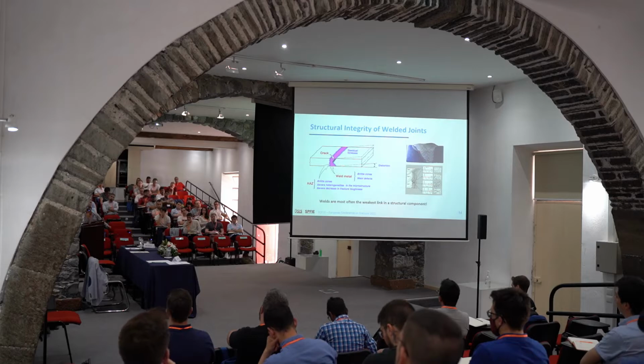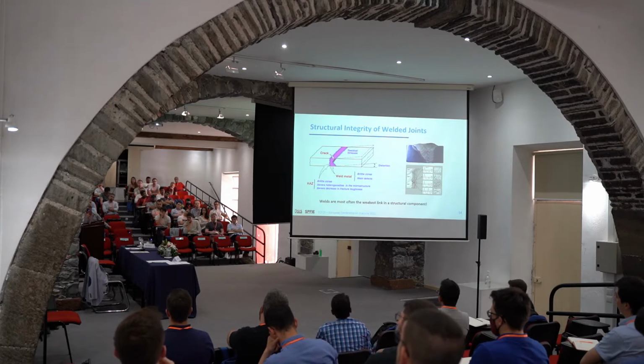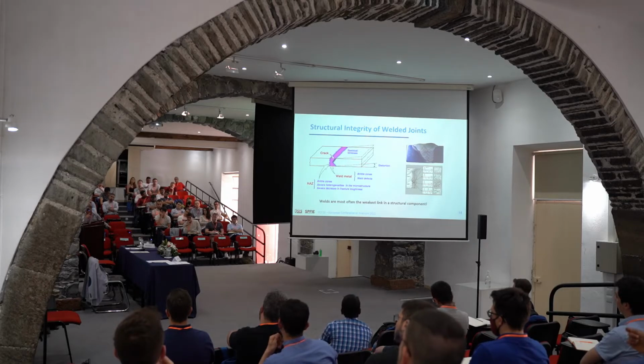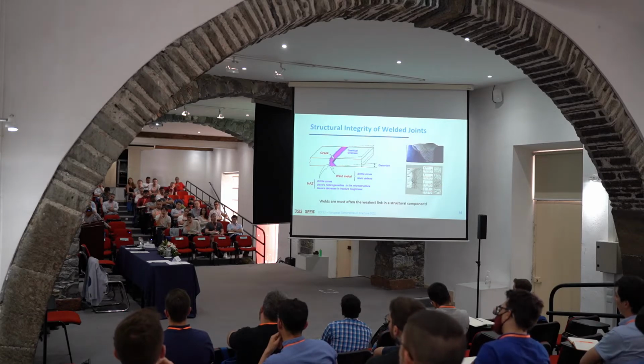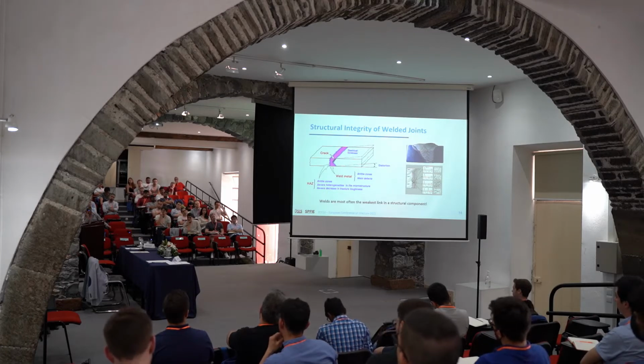If you have, for example, what's the standard way of assembling the airplane fuselage, you have a rivet, the plates are sort of superimposed. So if a crack develops in one panel, it won't propagate to the other panel. That's one of the reasons why the fuselage is not welded, especially for aluminum. Of course, I'm not discussing composites like the new trend. But in most structural components, the way we put things together is by welding.